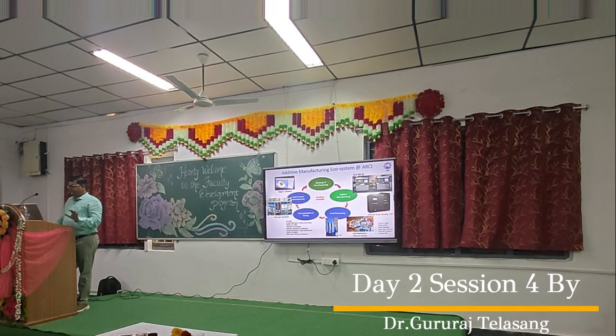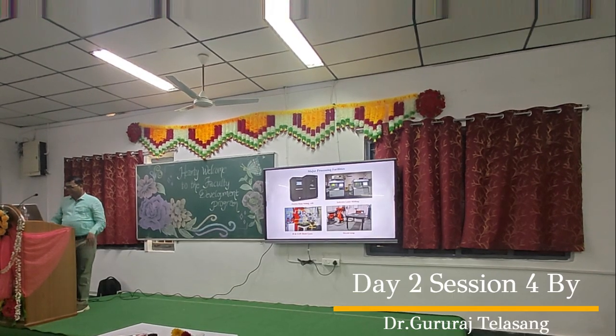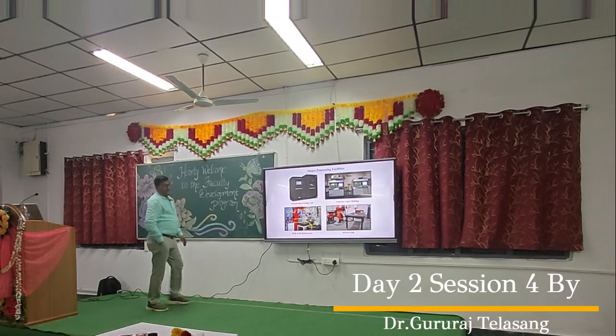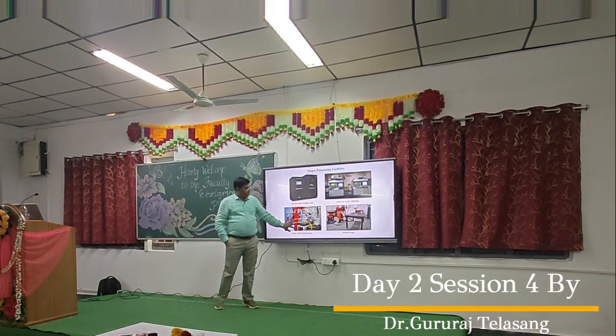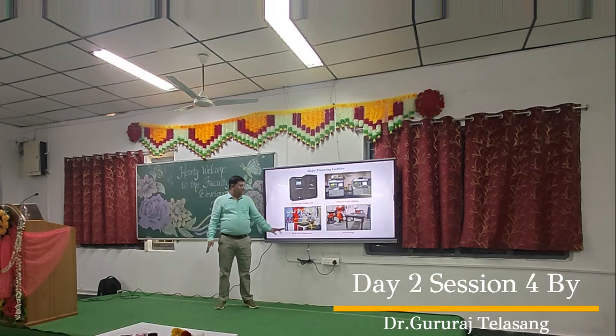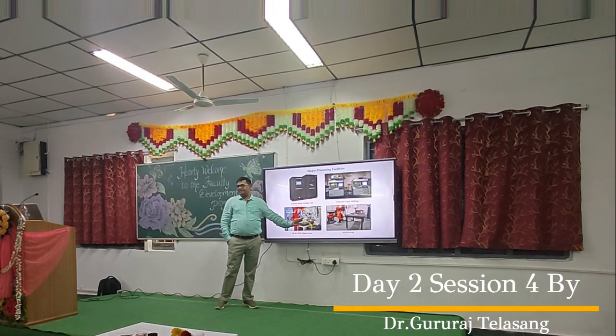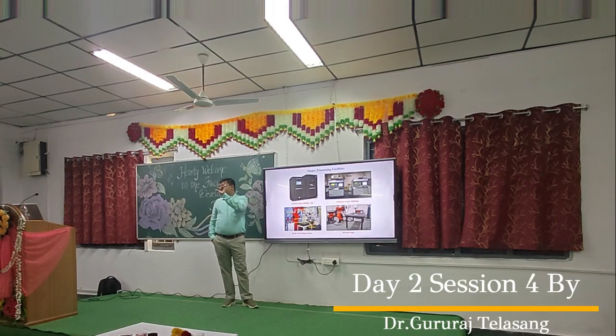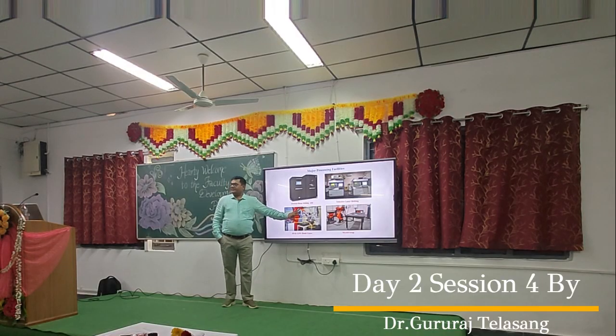With this facility, this is another thing we have, called DED. I told you DED, right? This is something similar to DED. It's called laser cladding. If you put the entire thing in an inert atmosphere, that will become DED. But the laser they use will be much finer. Here we are using a 2 mm spot size, which will give 1 mm thickness. Every layer will be 1 mm. I told you 300 micron, right? So that is different, much more near net shape. This will be a little rough, but better than welding, meaning wire arc additive manufacturing.